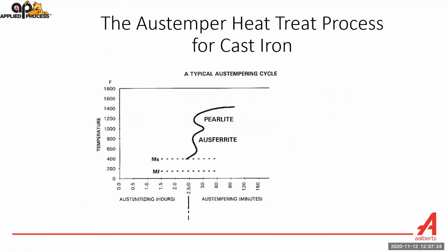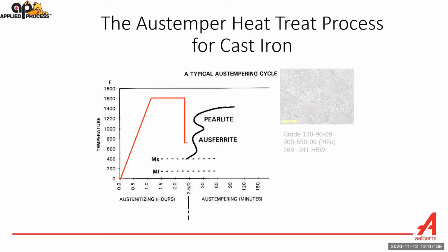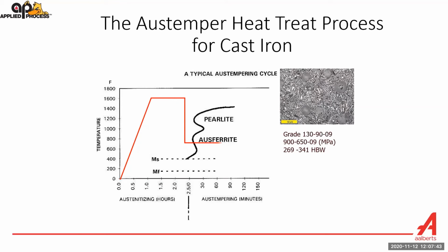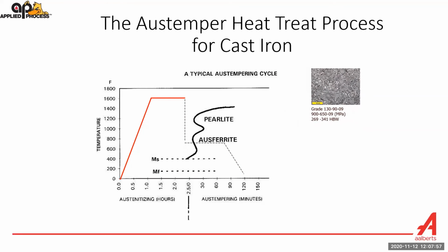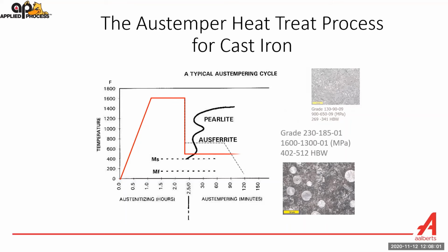So again, the steps in the austempering process: we start at room temperature and elevate the part to about 1600 degrees Fahrenheit, which would be typical. We hold for a period of time while carbon diffuses out of the graphite nodules and into the matrix. And then we quench. We're quenching in molten salt, so we're at high temperature. If we quench up around 700 degrees Fahrenheit, pretty hot, we get grade 1 ADI. You can see what the microstructure looks like there. It's that acicular or needle-like structure. If we follow the same path but quench at a lower temperature, we get grade 5 ADI, which would be used in the agriculture or construction industry, and it has a hardness of 402 to 512 Brinell. So we can take the same part and, by quenching it at different temperatures, get to the different grades of ADI. That's how it happens.